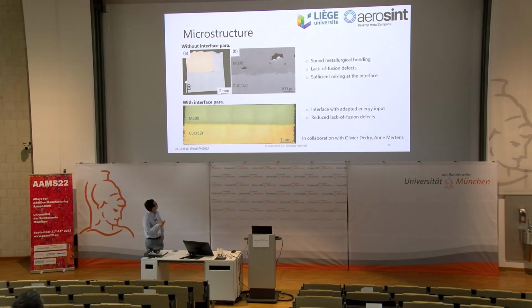However, we do see very promising things. So if these two materials are well intermixed at the interface, as you can see here, due to the different contrast from the element. And then, of course, the logical thing is that, because the first few layers require different energy density, we also did a trial to use a different energy input. So actually we found a very interesting result. We can really remove all these lack of fusion defects.